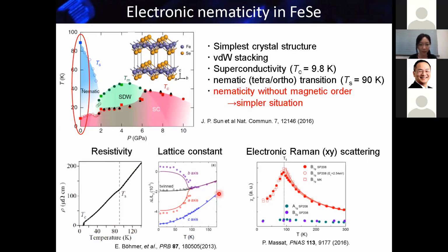This is the resistivity and the lattice constant. The orthorhombic state shows up at 90 Kelvin. For the nematic fluctuations, very nice electronic Raman scattering studies have been done. Electronic Raman scattering can derive a physical quantity corresponding to the nematic susceptibility, and they find that it's enhanced toward this transition temperature, with a peak like this. So there are many studies on nematic fluctuations and nematic transitions in this material.